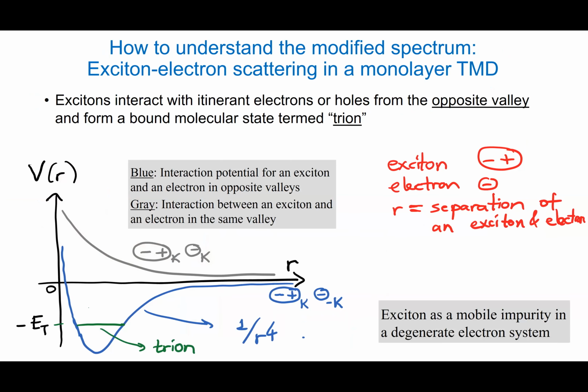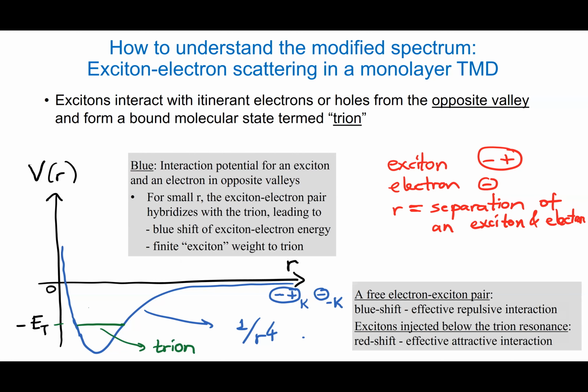We can resort to a picture that, if you're familiar with atomic physics, you would appreciate. We can think about the modification of the spectrum as a scattering problem between an exciton and an electron. Okay, so this will depend on whether the electron and exciton occupy the same valley or opposite valleys. Let me just focus on the opposite valley case. I won't go into detail why there is no bound state in the other one, but in this case, the potential is that of a neutral but polarizable particle and a charged particle, right? So the interaction between the two at long distances is 1/r^4.